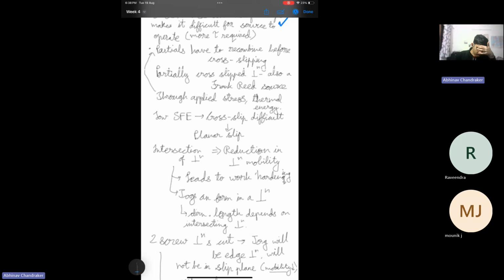This tendency for recombination will depend on what is the stacking fault energy for that material, because as I said, the partials are separated by a stacking fault, and if the energy of that stacking fault is very low, the partials will be far away from each other and it will be difficult for them to recombine. While if it is very high, the partials will be very close to each other to reduce the stacking fault area. And since they are close, it's easier to recombine. So cross slip will be easier.